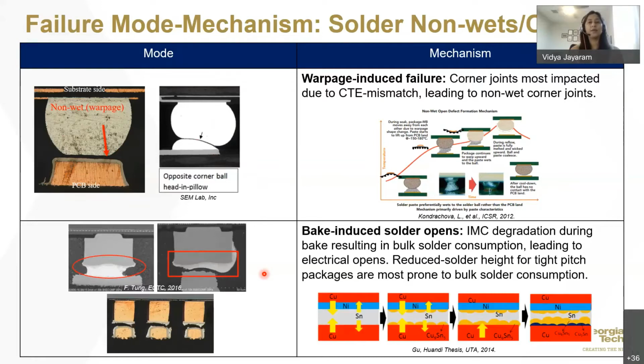Another interesting mechanism for having a non-wet or open are bake-induced solder opens, and that is again more thermal stress induced. At higher temperatures with some level of humidity during bake, this can result in the solder being consumed. The free solder gets consumed to form the intermetallics, and that can lead to reduced solder volume in the actual bump and lead to non-wets or opens. Now, this would be a higher risk for reduced solder heights that you typically see at chip level that are more prone to this bulk solder consumption.